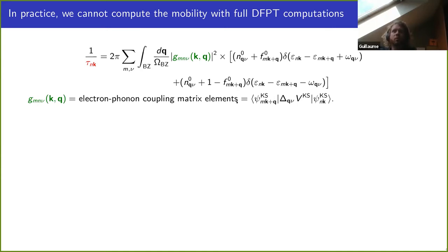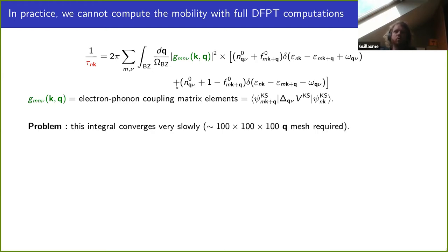In practice we can compute these lifetimes using ab initio methods: DFT for the band structure and DFPT for the phonon frequencies and matrix elements — so we have everything we need to compute the lifetimes and the mobility. The problem is that this integration over q-points converges very slowly; we typically need millions of q-points, but DFPT is not cheap. Performing a few DFPT computations is fine, but on a mesh that dense — good luck.